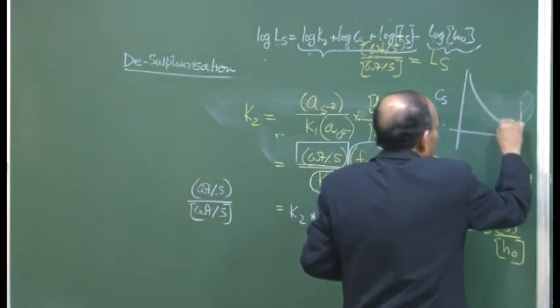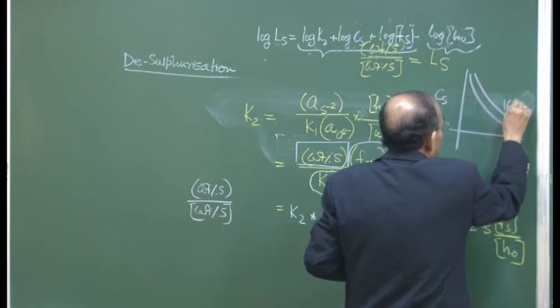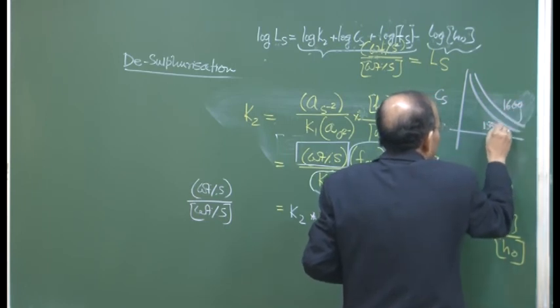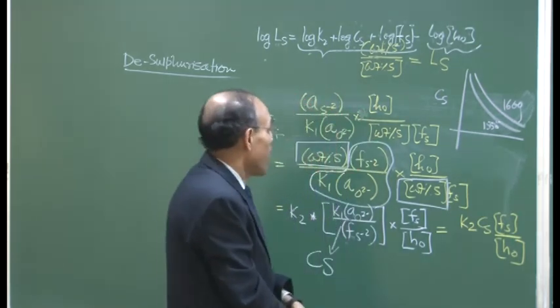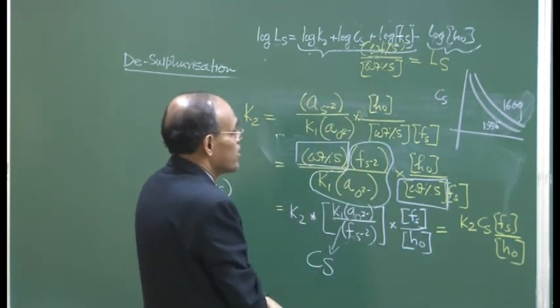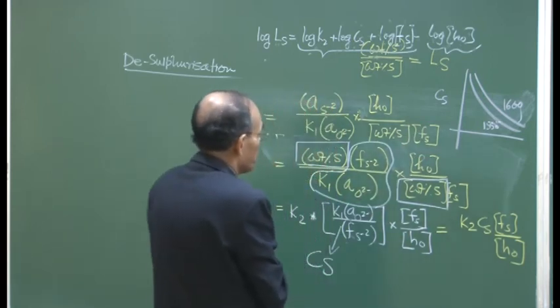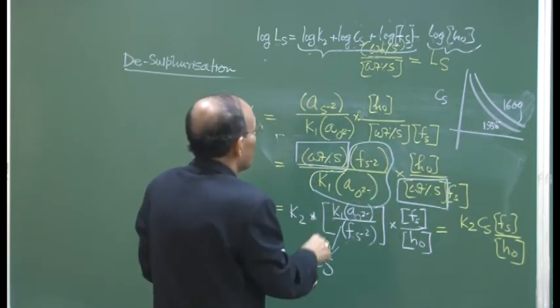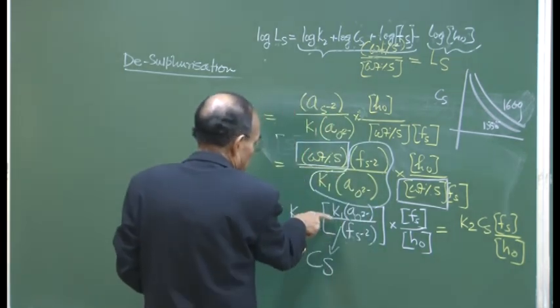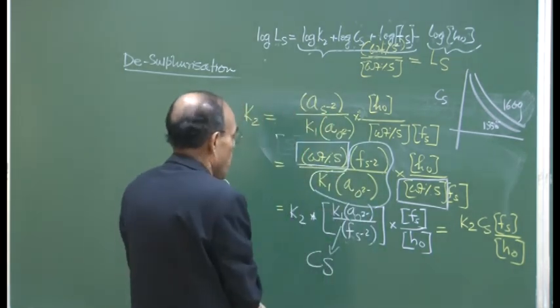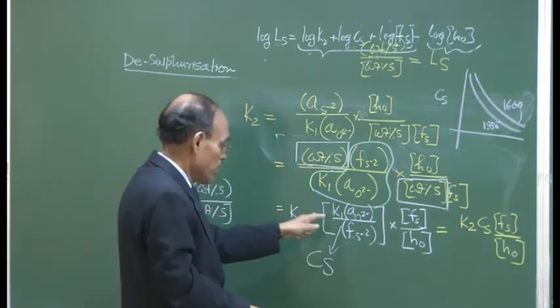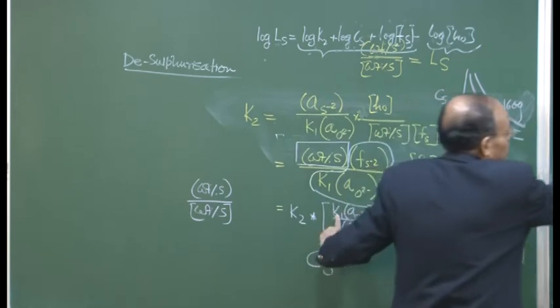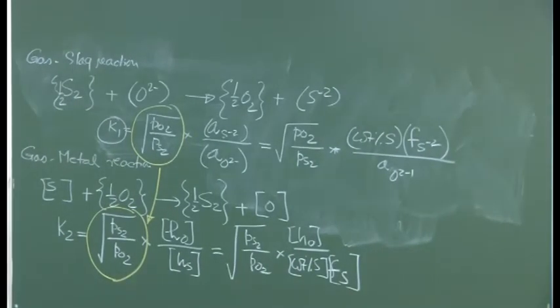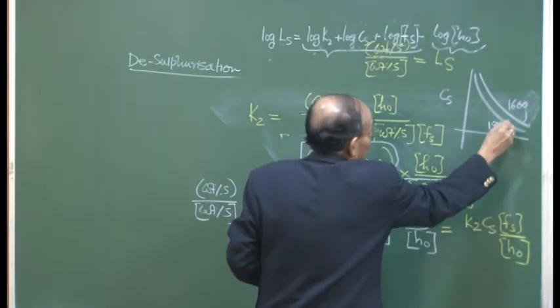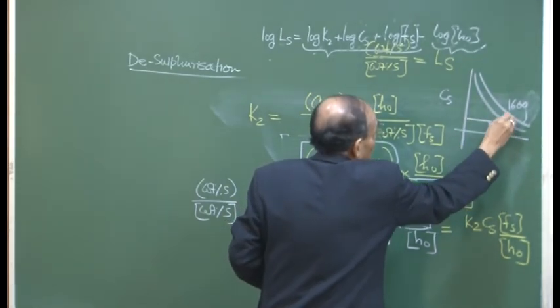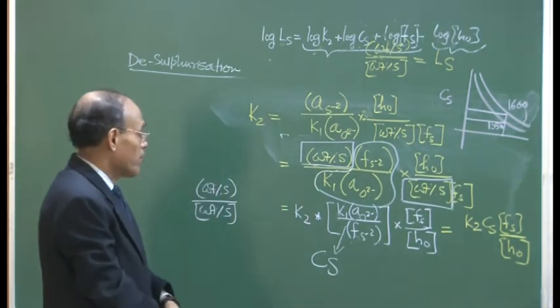And if you plot two different temperatures, one could be 1600 for a given slag and the other could be 1550, then you see the higher the temperature, the higher the sulfide capacity of the slag. And this basically comes out from the fact that this K1 is a function of temperature. So this equilibrium constant is a function of temperature, and it shows that if you increase the temperature, you do get an enhanced Cs, or sulfide capacity, of the slag.